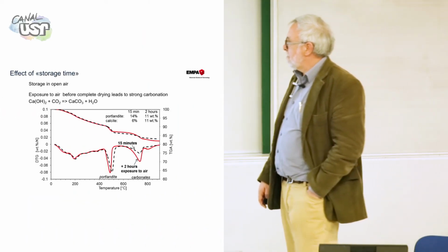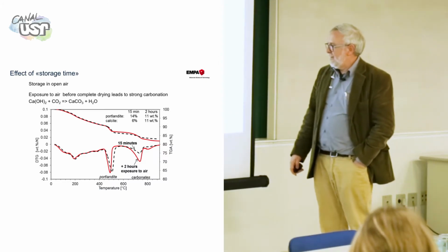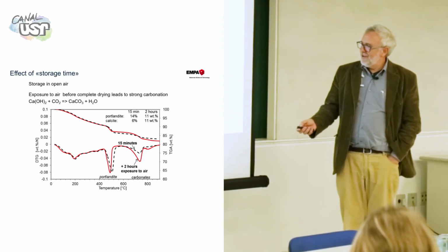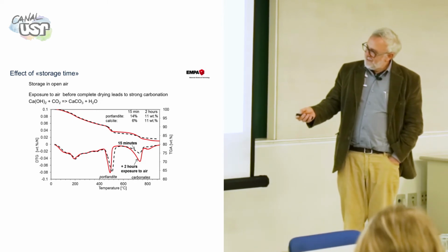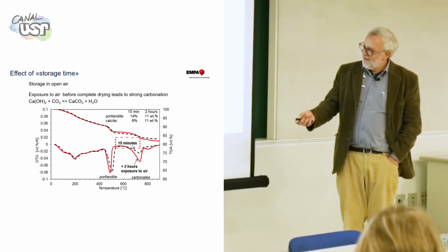Storage time. We are talking here about the amount of carbonates, 15 minutes in the air, and here is 2 hours in the air. So you grind, as Karin mentioned, you grind it, you put it inside a container with something like very low relative humidity and something to suck out the CO2. You have to do that. Otherwise, it's going to carbonate. So that's very, very important.